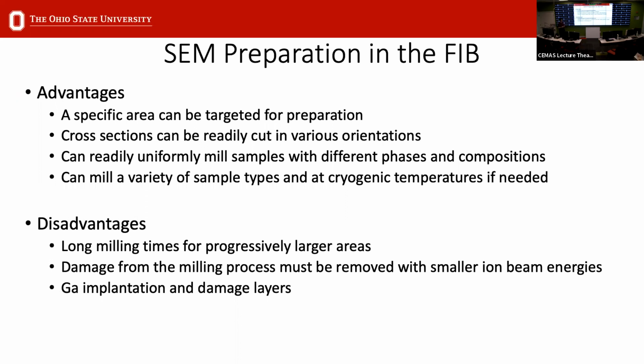So I started with the conventional ways, by polishing by hand. In certain instances, sample preparation can also be done in the FIB. This is the focused ion beam, which is usually used for preparing TEM samples. In this case, you'd use a focused ion beam, historically of gallium ions, but in current systems, there's also the option of using plasma, such as xenon, argon, oxygen, or nitrogen. I'll talk a little more about the differences in those.